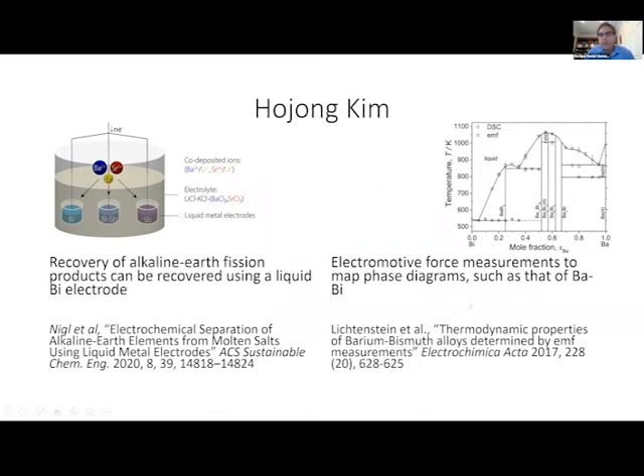Another paper that I found quite interesting is this one on using electromotive force measurements to map phase diagrams. Because in that case, basically you can use these types of measurements, again, through this electrochemical approach, to be able to map out phase diagrams by directly mapping out what the Gibbs excess energy is, what activity values are for different species and different, for example, in this case, salt mixtures, right, or alloys.